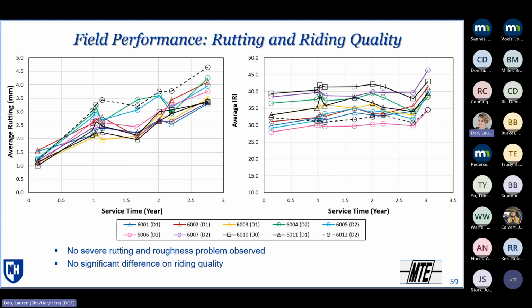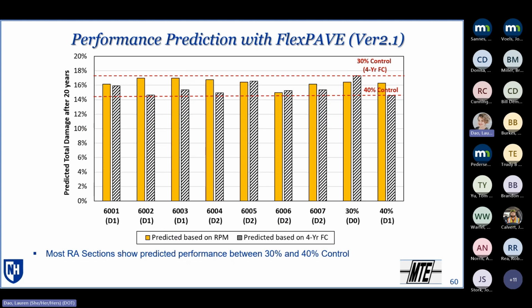Now, in addition to the field performance, we also did some modeling using the dynamic modulus and the direct tension cyclic fatigue testing results. Looking at these performance predictions, we did it with two different material properties. We did it with the as produced material, which is the yellow line, and then with the 4-year field core data. And you can see, again, not a whole lot of difference in terms of the projected performance between these two sections. And all of them are falling between the 30% and the 40% control materials.